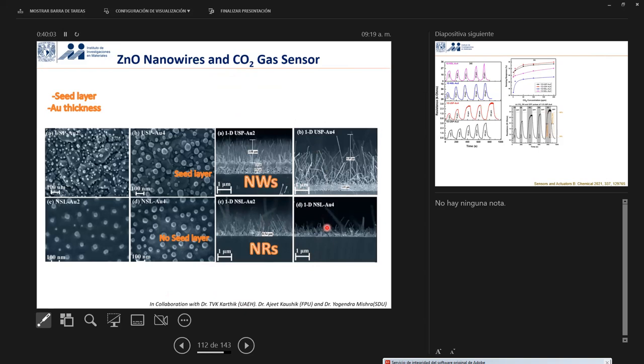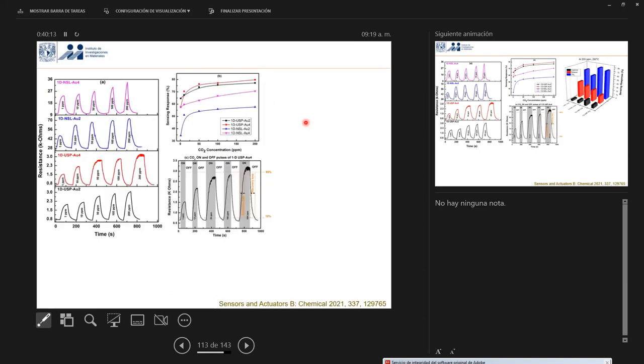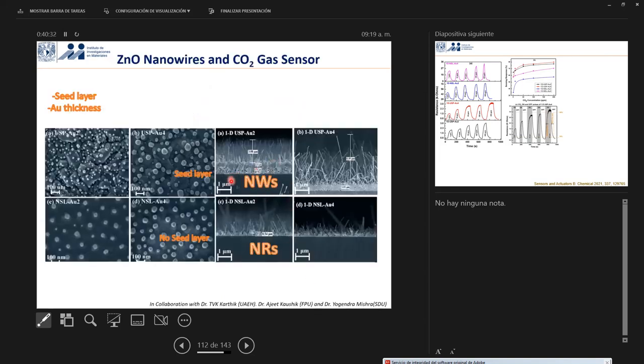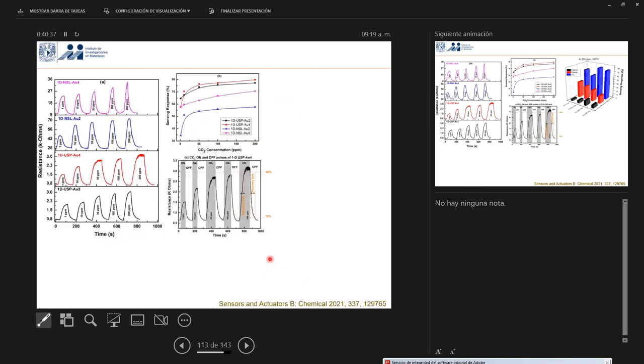Again, in this case, we were successful in controlling the morphologies of these nanostructures, and the aim was to check the sensing ability of these nanostructures. But we found that these nanowires were better. They had a better sensing quality. And nanorods were less sensitive to the detection, but they were faster actually. So there are two main conclusions. If we want highly sensitive structures, we can go for nanowires. If we want a faster response, nanorods. Okay, so that was the difference in the two structures.